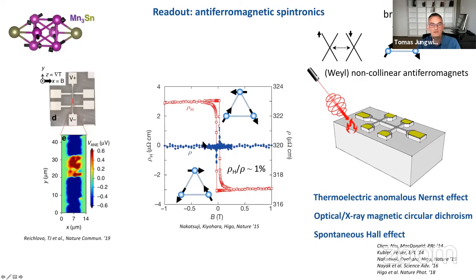Now, here is an example of the experimental demonstration of anomalous Hall effect in this non-collinear antiferromagnet manganese tin. But what I'd like to emphasize again is that, as in simple magnetic films, the signal is relatively weak. The relative size of the Hall resistivity that you measure relative to the longitudinal resistivity is again of the order of 1%. Compared to ferromagnets like iron, for example, this is a similar value. It's just the problem of simple films generating these relatively weak magnetotransport responses. And again, one way to look for singular effects, much larger amplitudes, is to try to work with some topological features in the electronic structure.